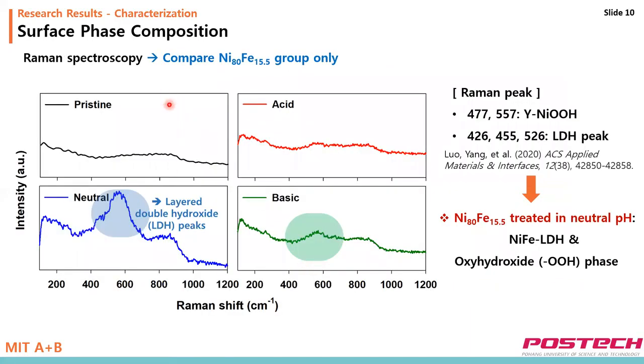In addition, the surface phase composition of the treated electrode was analyzed by Raman spectroscopy. In the neutral pH treated electrode, the Raman bands are related to gamma nickel oxyhydroxide and layered double hydroxide peak. Therefore, the form of oxyhydroxide or hydroxide can affect the increased UOR activity.